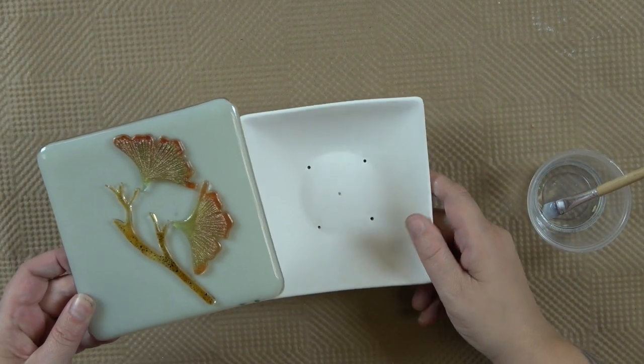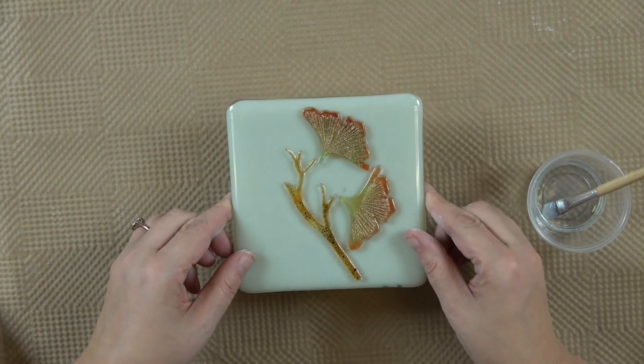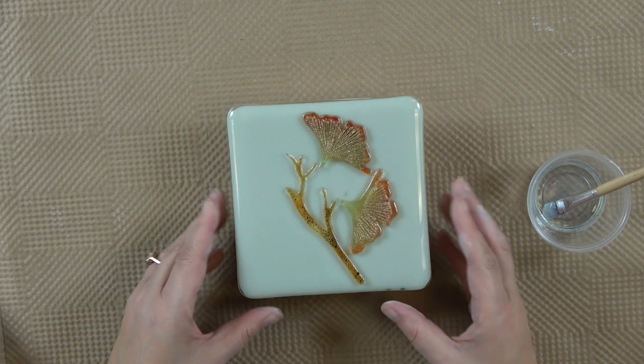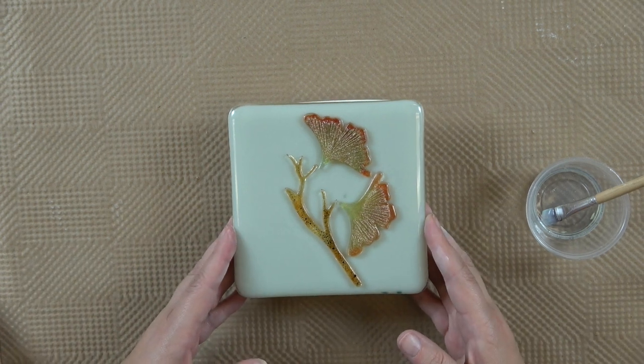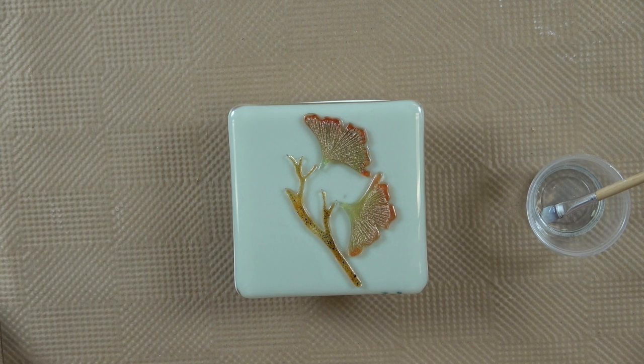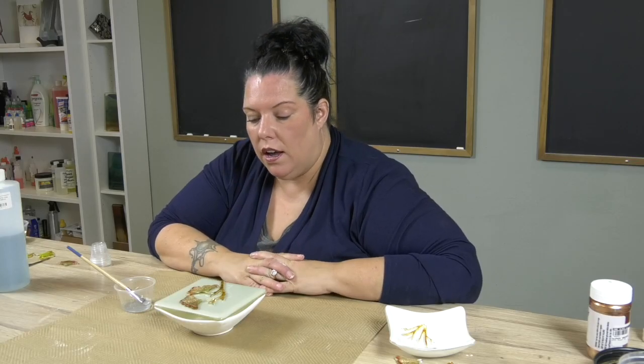Take this guy. All right, put it on your kiln shelf, obviously. This is even going to be a little bit over. I would say it's about 1/8 of an inch over. It's okay, we're slumping low. It's going to go low and very, very slow, and we're gonna hold a long time. That schedule will be ginkgo bowl slump, but I strongly suggest that you use that slump schedule for uneven thicknesses for all of your fused glass needs, guys, okay?